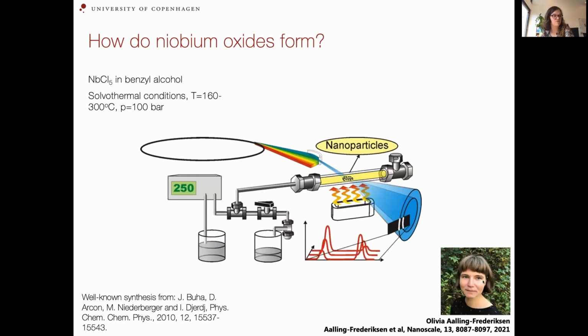So this is my PhD student Olivia, who has been working on this, and we wanted to study a fairly simple synthesis method, which is actually used for making a lot of different oxides. You take a chloride salt, and you put it in benzyl alcohol, and then it's a solvothermal reaction. So you heat it and keep it under pressure, and then nanoparticles form. This has been studied for a lot of different oxides, because you can make fairly high quality nanoparticles in this very simple way. So we studied this in situ. We shoot X-rays on it at the same time as the synthesis goes on, and then we can collect data and follow the reaction.